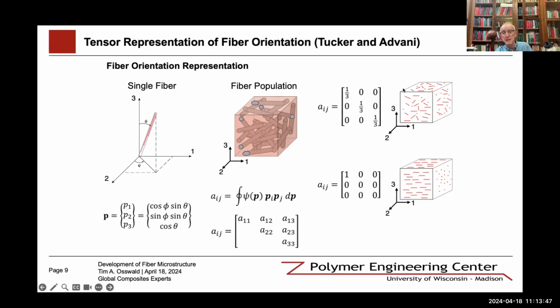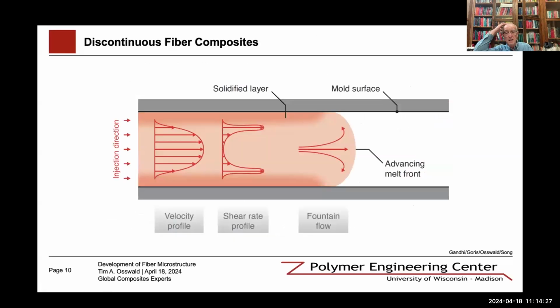But if you see the A_ij on the top, a random orientation would be represented by A11, A22, A33 as equal parameters. They add up to 1. So that's one thing that makes it easy. So 1/3, 1/3, 1/3 simply represents a random orientation distribution. If they're all oriented, let's say in the one direction, as the lower right-hand side shows, then the orientation tensor would have a 1 in the A11 term, and the other ones are 0. So this is just a very brief description of the orientation tensors that I will use in the next few slides.